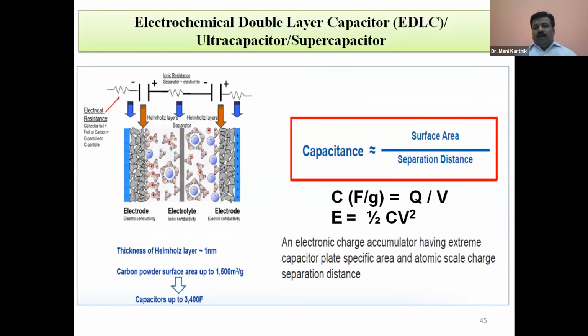If you see the fundamentals of the electrical double layer capacitor, as I said, the capacitance is surface area divided by the charge separation distance. Here, this is the separator. As I said, the separator is ionically conductive and electrically insulating. That's why, without a short circuit, you can put the two electrodes, positive and negative, separated by insulating material. Then we put in the electrolyte. This is the current collector. Basically, we are using carbon coated aluminum foil or aluminum foil as the current collector in both cases. The electrode is coated on the current collectors, and this is the cell made.